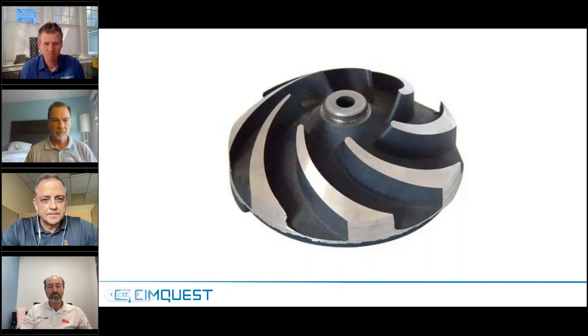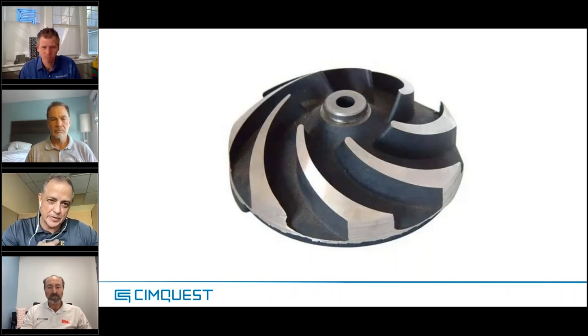The material is titanium — confirmed. This could fit in our machine. It's rather large, so it would take some time to print, and we could counter that by adding more lasers if time is critical. The surfaces are pretty vertical, so support structures wouldn't be much of an issue. Titanium is a reactive metal, so if this is for a hobbyist looking to buy a printer, I would not recommend laser powder bed due to the complications of titanium. But for a proper installation, definitely printable in laser powder bed.